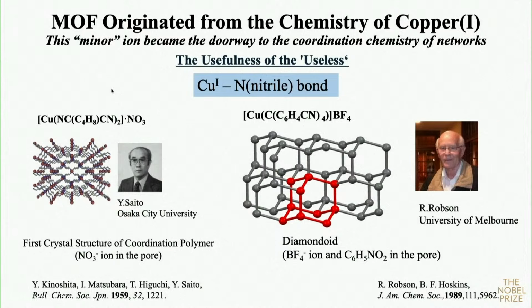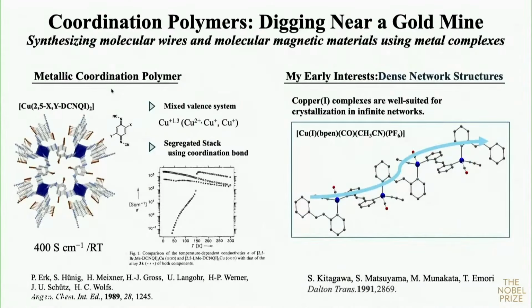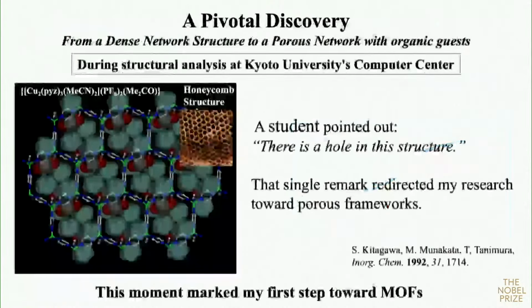the network formation principle. Simultaneously, Hünig synthesized this kind of interesting material using the DCNQI ligand. These DCNQI ligands show high conductivity. This is metallic conductivity. I was very interested in this system, and we were interested in the fully densely packed structure, because for the conductivity pathway, the dense structure is good for these properties.